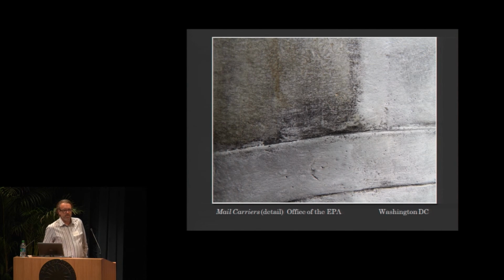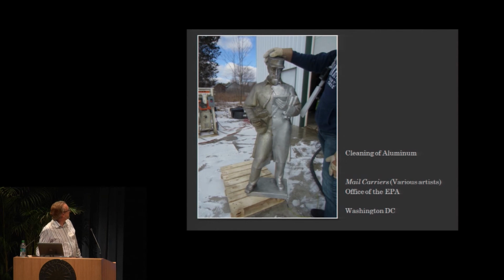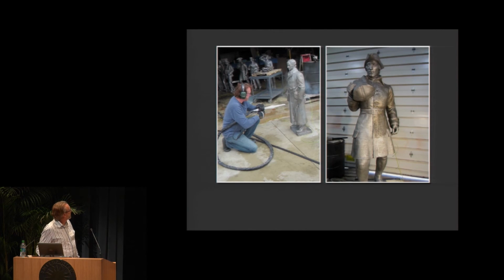This is a close-up of the surface. This is a clean surface on the right, the dirty surface on the left. And as you can see, we're not adding any profile to the surface. So we felt it was safe enough to proceed. And the white stuff on the ground is actually snow. I did this in the middle of winter and not dry ice. And here's some shots of during cleaning, kind of the removal of the grime.